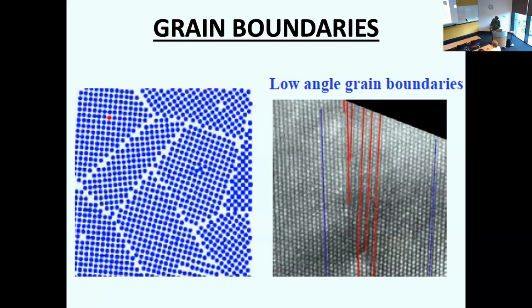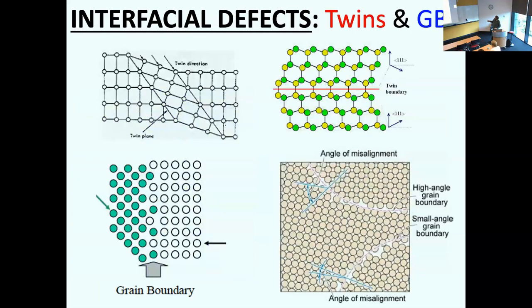Okay, so if you have a square that is undergoing some phase transition to a rectangle, you have two kinds of orientation. Both of them are equi-energetic. They must coexist. But how should they coexist? They coexist such that the elastic energy is minimized, so you need a mirror plane. So that's why it's called a twin boundary. And similarly, you have other kinds of grain boundaries and whatnot.